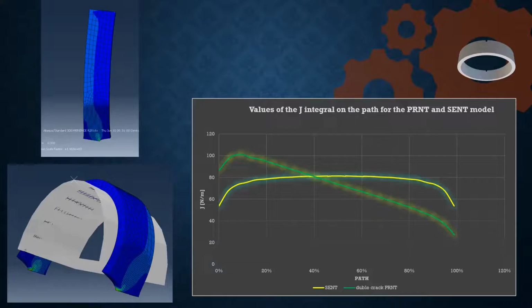We are working on determining the influence of the ratios R/W, R/T, and A/W on the value of the stress intensity factor in the PRNT models. Also, one of the goals is to verify the procedure of testing specimens with one groove, which will avoid the possibility of uneven crack growth in rings with two grooves. In the following period, we will deal with the parameters of elastoplastic fracture mechanics, as well as the examination of rings cut from steel pipes.